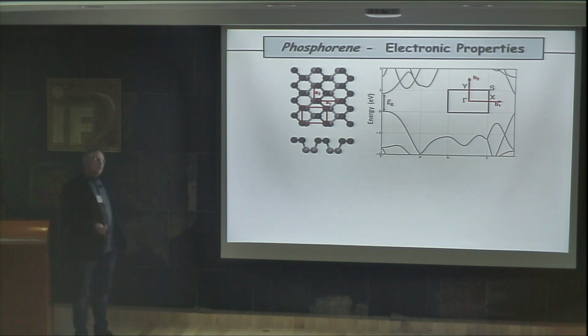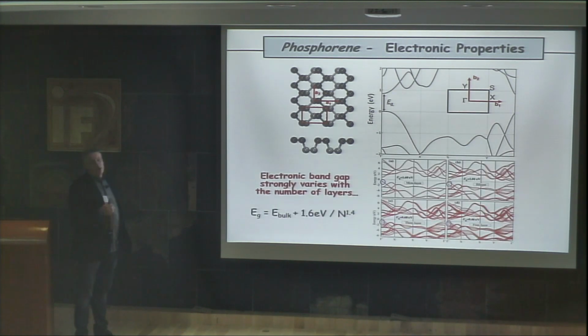And what is extremely interesting in this case is the fact that the electronic band gap of the system depends on the number of layers. So you can go, for example, from a monolayer with a 1.6 eV band gap to the bulk material, which is about 0.45 electron volts for the band gap. So you can really play with the number of layers and have a different band gap depending. And there is a kind of empirical law to get the band gap from the number of layers that you have in the system.